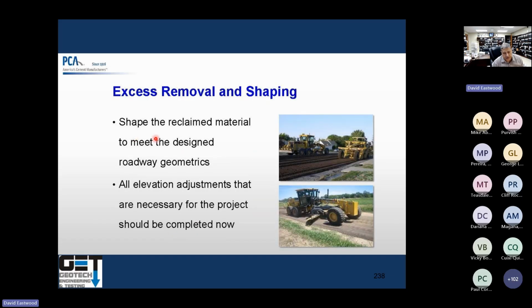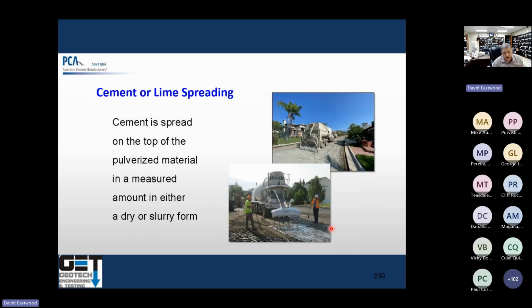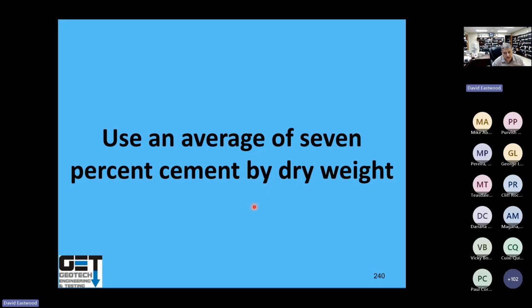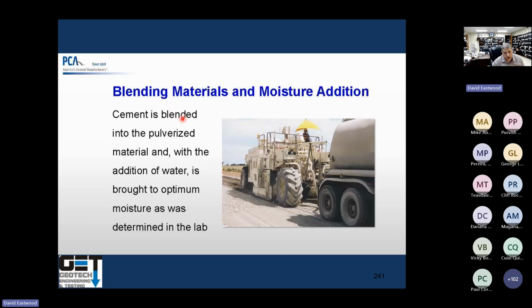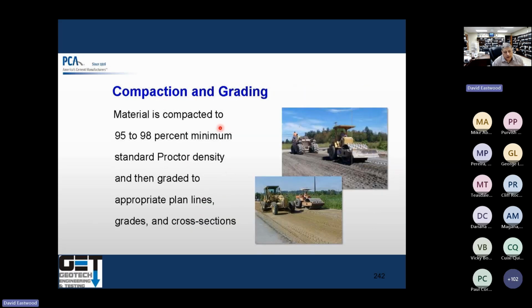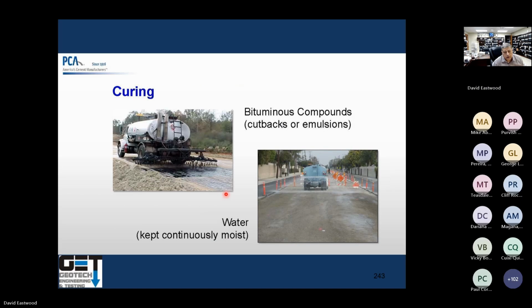You remove the excess material, shape the reclaimed material to meet the design. Make sure you got all the elevations. Then you bring the cement in and mix with it, usually about 7%. You mix it, average of 7% cement by dry weight. Blend it in and compact it right away. Water is added, brought to the optimum moisture. Got to compact 95 to 98% of proctor density. Then you let it cure for a little while, either add water to it to let it cure, or you put a tack coat.